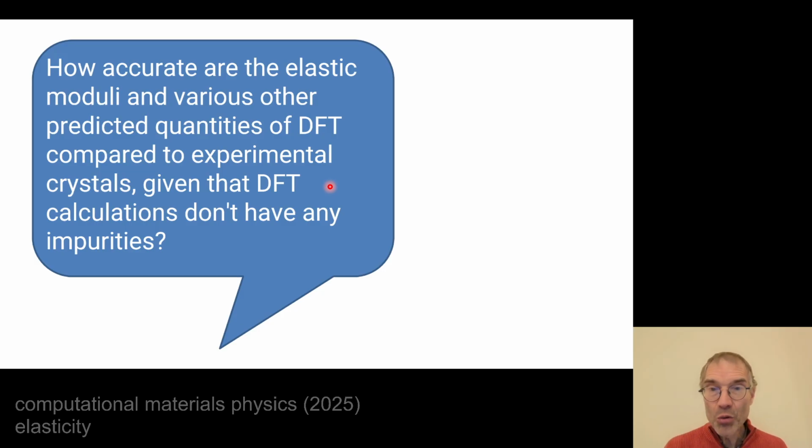I can already tell you, in many cases, you don't see too much impact. It's the basic matrix, the basic host crystal that determines most of the elastic constants, and that is why values that have been calculated for single crystals, for pure crystals without defects, they are often good enough. They are reasonably in agreement with experiments, and they are so much easier to get than the similar experimental value that this is the thing that people will use.